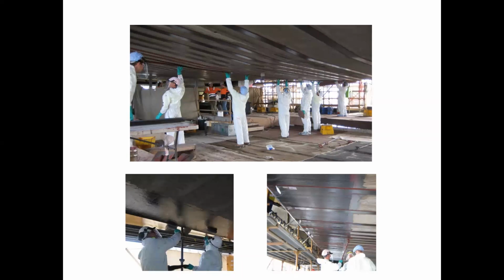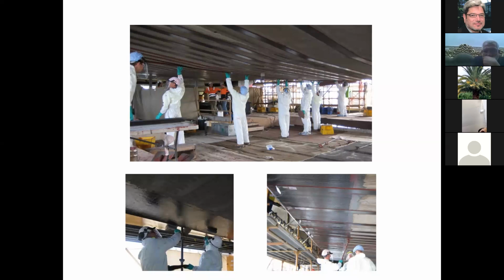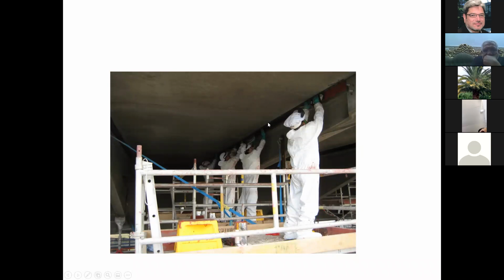So this is during the application process. As you can see, this is, as I said, very light material. The number of workers here carrying one strip is not because it's heavy, but because of the alignment. As you are applying this with the epoxy, you needed a number of people to ensure the proper application of the FRP system. This is work on the cantilevers as well, the top of the cantilever, putting laminates on the top flange of the cantilever beam to increase its flexural strength.